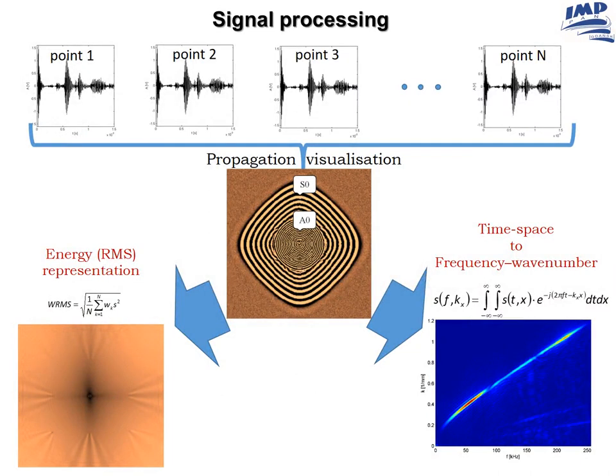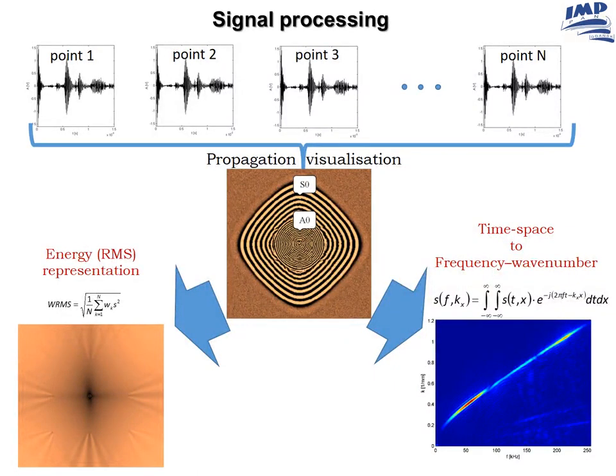Having a set of registered points — here we have N points gathered as an example — we can visualize the propagation of the wave. Such results can be represented in the so-called energy representation, and discontinuities encountered by the propagating wave can be visualized. We can see several wave scatterers in this example. On the right-hand side we have the frequency-wavenumber representation that allows us to see how the wave number and wave phase velocity change with frequency in the investigated material.